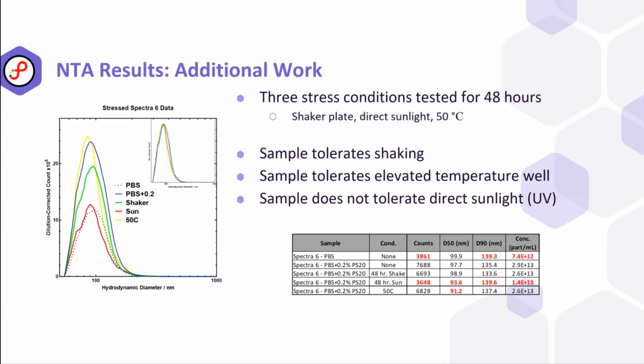And what we can see, compared to the PBS plus 0.2% polysorbate, is that the sample tolerates shaking very well, which is not unexpected. Polysorbate is typically used to stabilize the surface of these biomolecules in suspension, and that helps to protect them against the surface charge density that you see when you shake or you have air bubbles entrained into the suspension. The sample also tolerates elevated temperature relatively well, though we still are seeing that shift to smaller size and the narrowing of the population. So that's still not quite explained.